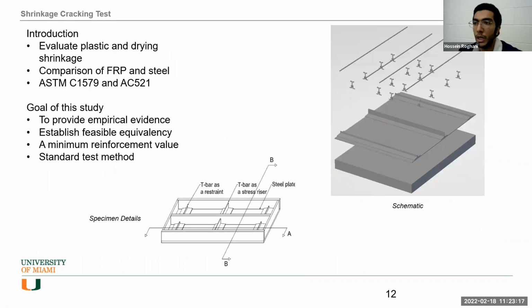Now I'm going into really what we are doing in the lab in terms of evaluating plastic and drying shrinkage. In this test, we are evaluating the plastic and drying shrinkage of the concrete that is reinforced with fiber reinforced polymer compared to the conventional steel reinforcement, and both can be rebars and also meshes. And we are going to demonstrate the equivalent or better performance of the FRP in comparison to the steel. So we have to say it performs at least as well as the steel, so we can replace it.